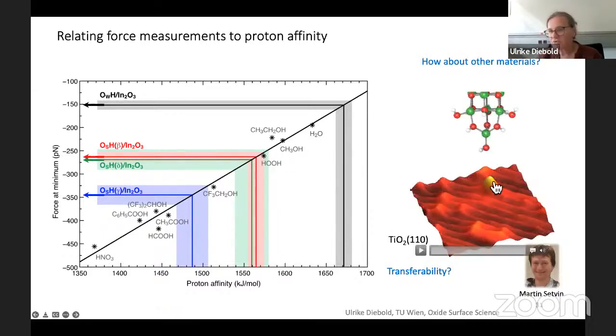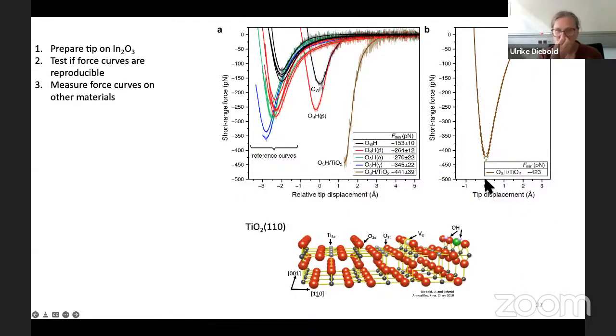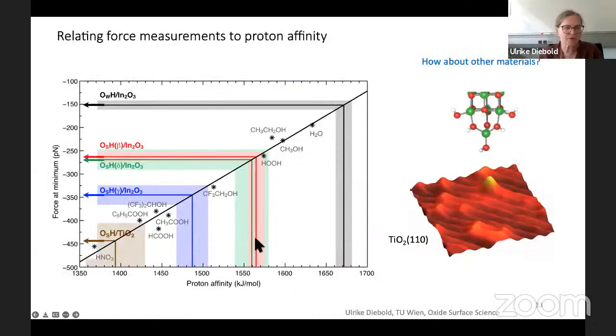This is the TiO2 surface I showed before. This is a hydroxyl here. By the way we do it, we prepare the tip on this indium oxide surface, where we have a good measure. Then we go to another material, measure force distance curves there, and then go back to the original one to see it's close, and do also the modeling. And then we find the surface hydroxyl on this TiO2 is, as expected, much more acidic.